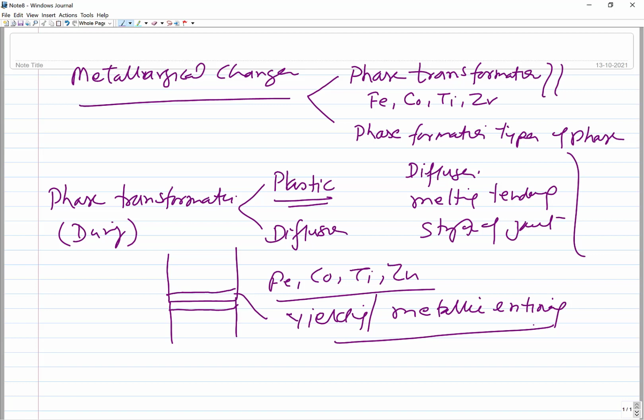Similarly, this kind of behavior can also be observed in terms of recrystallization. So not just the allotropic phase transformation, but recrystallization also leads to a situation where the metal tends to behave in a more plastic manner, and the diffusion coefficient is enhanced. Both these are helpful in facilitating diffusion bonding. The improved plastic behavior facilitates increased metallic intimacy at the interface, and the increased diffusion coefficient leads to faster diffusion across the interface, and so to diffusion bond formation.